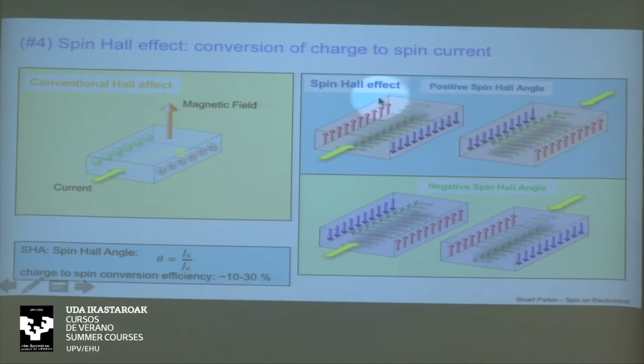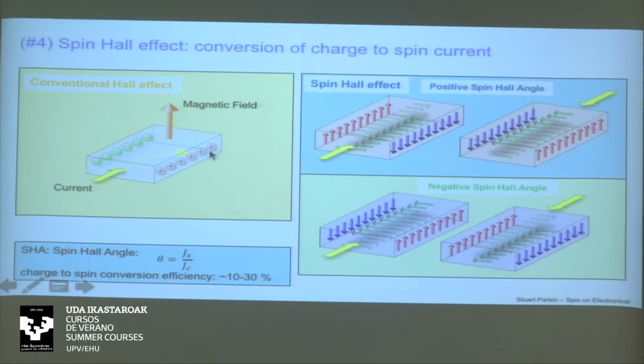So on the top face, in this particular example, the spins of the accumulated electrons are pointing to the right. But on the bottom interface, they will point to the left. And this essentially is why these interfaces with the cobalt-nickel-cobalt racetrack give rise to opposite effects.